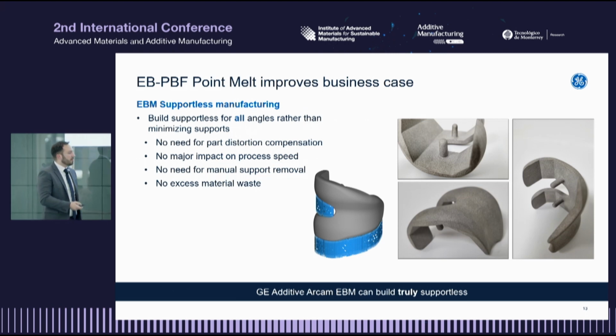And then finally, point melt can help in a business case scenario. The classic approach for supports in electron beam, because we can nest in space, is that not everything needs to touch the actual start plate itself. Where we need to remove those supports, they're usually 20 millimeters long or so. You can break them off with a pair of pliers and maybe some tweezers. By hand, essentially, you can do this. But it takes labor. Somebody needs to come and actually do the breaking of those components. If I can print a component that's totally supportless, the part gets turned around a lot faster, I'm not paying for that labor, and therefore the business case for these components is improved. It's more beneficial to go down an additive path.